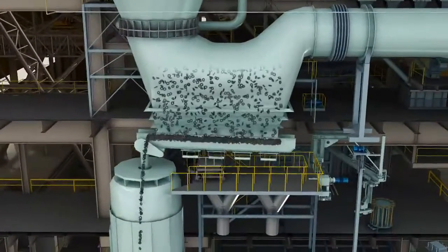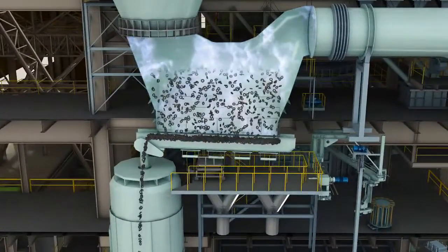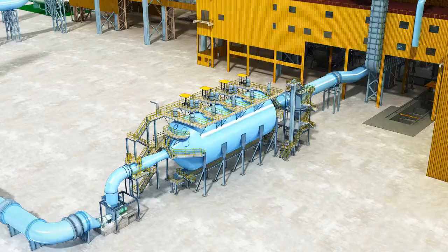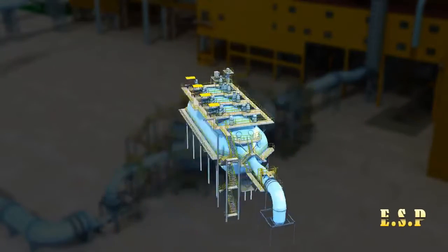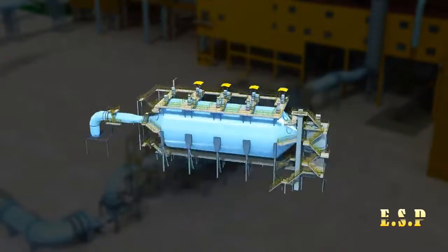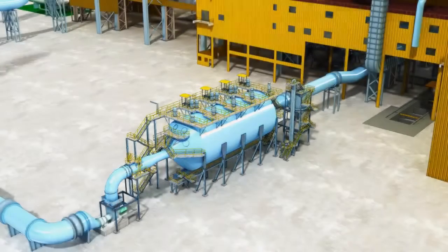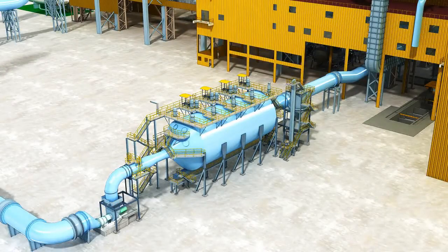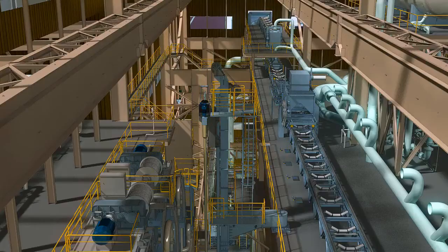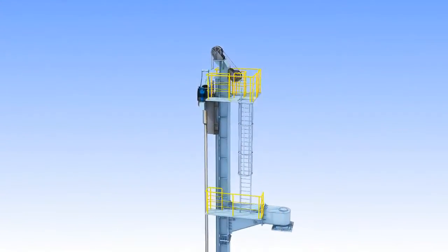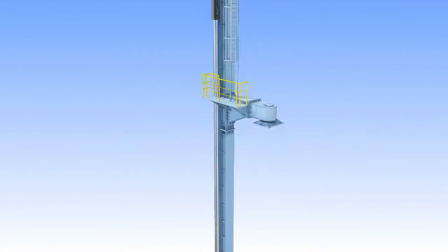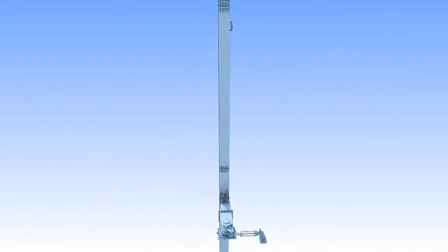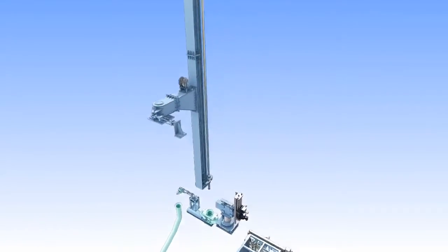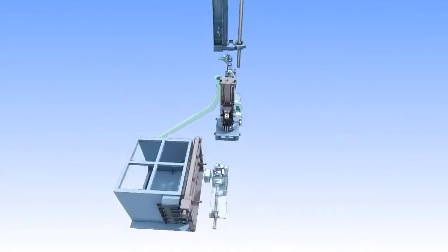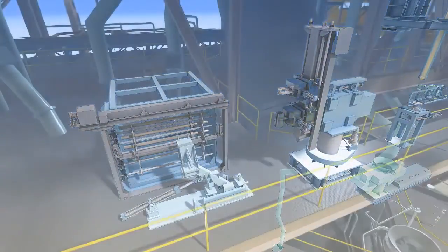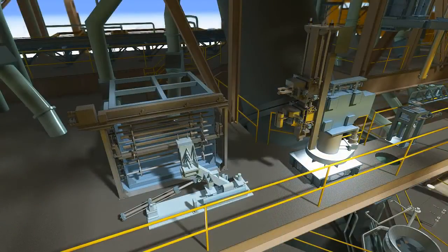The collected dust is discharged through the chain conveyor, and second dust collection is performed by the electrostatic precipitator. The impurities inside the hot metal are removed during blowing, but to accurately predict the target temperature and the endpoint oxygen according to the steel grade, the ingredient is measured using sublance at 80% of blowing.